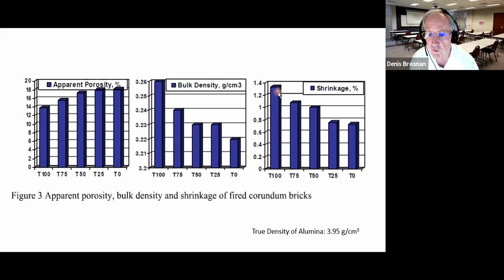And of course, they got just under 1.4% shrinkage in firing. The fused alumina is, of course, much larger crystal size. It's going to be less reactive than the tab alumina even. And so less firing shrinkage is probably expected.